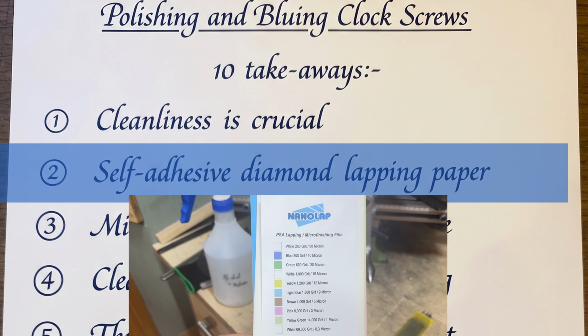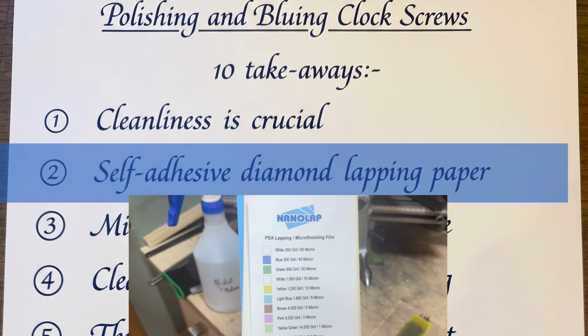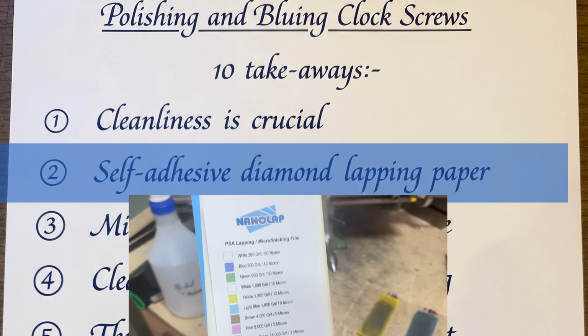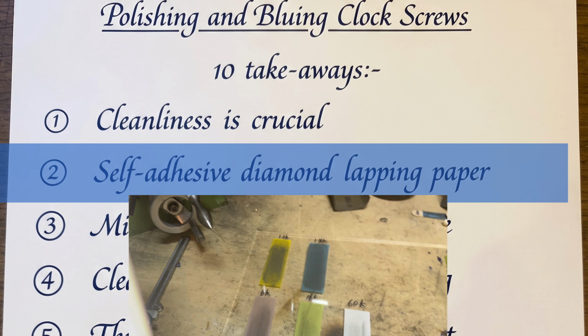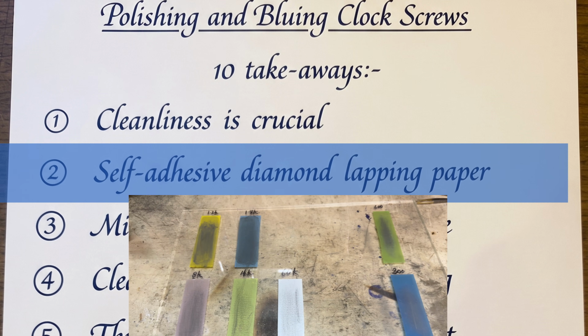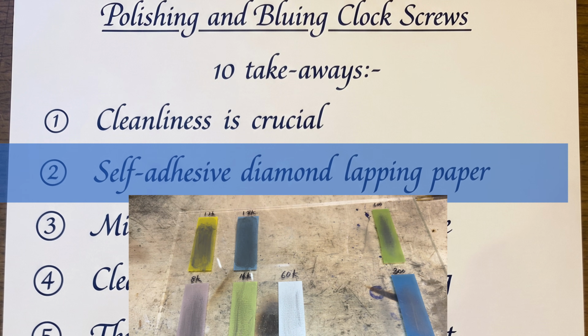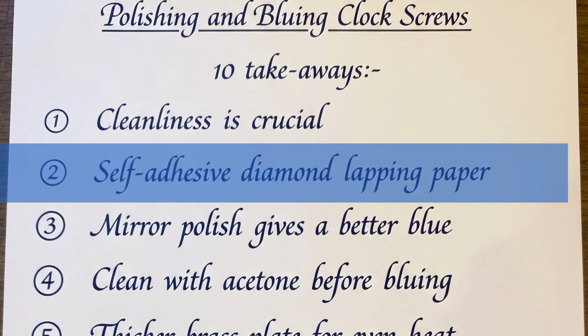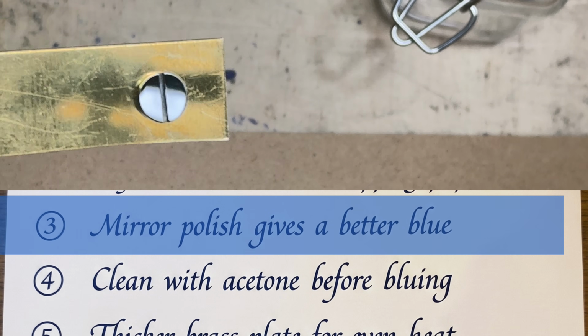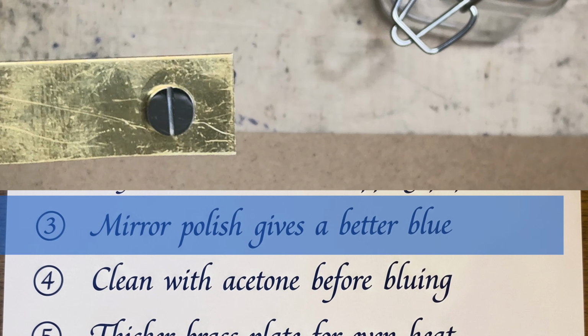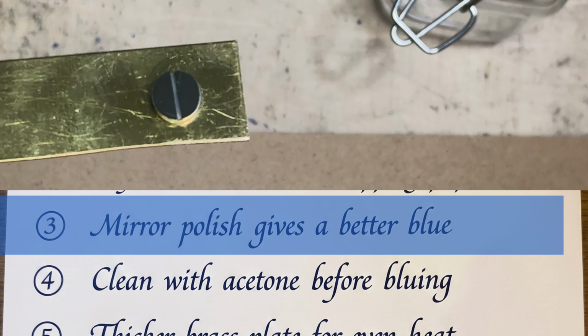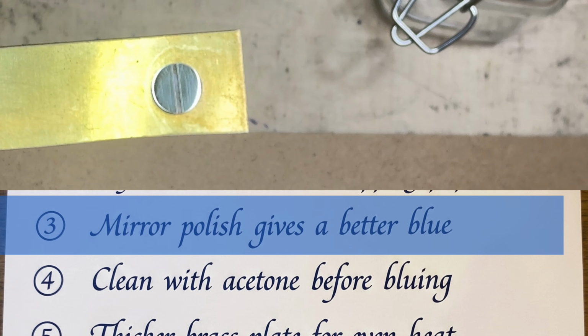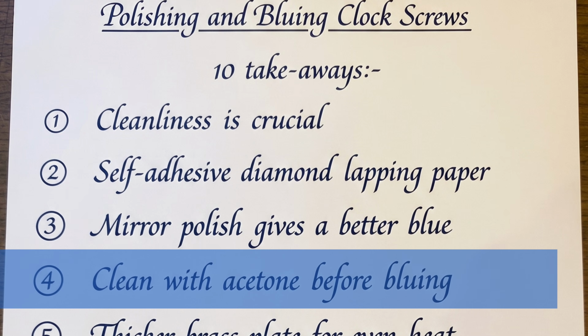These self-adhesive diamond lapping papers are absolutely fantastic for honing and polishing the screw heads. Ideally you would stick them to individual pieces of glass to prevent cross-contamination. My third takeaway is to stress the importance of getting a really good mirror polish finish before attempting to blue. You'll get a much more even blue. After the final polish, clean with acetone, not alcohol. Alcohol tends to leave streaks which can affect the bluing.